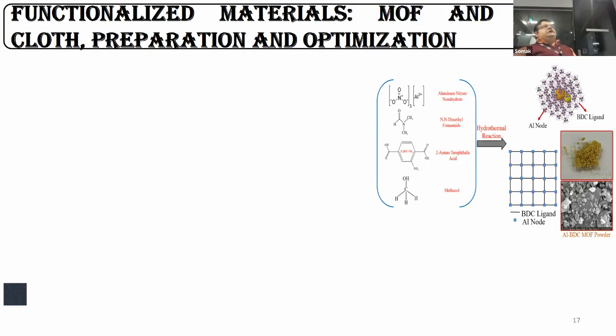A solvent, which is again DMF, the most abundantly available solvent in India, and a reactant by means of which the reaction mechanism can start is amino terephthalic acid, with an important hydroxyl group where we used methanol. I'll explain the reason for using methanol in this slide. By means of a hydrothermal reaction, we get an aluminum node which sits in the BDC, that is the terephthalate ligand, giving us this yellowish powder, which is the aluminum terephthalate MOF structure.